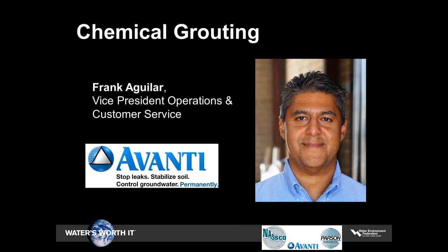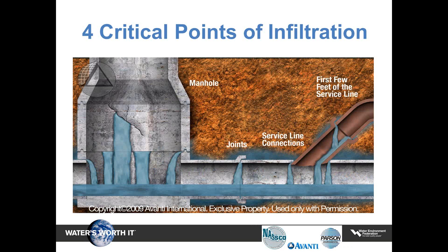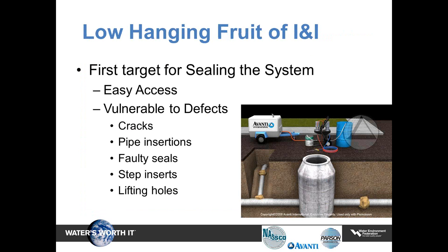Today I'm talking about how manholes are vulnerable to infiltration through cracks, pipe penetrations, faulty seals, and sometimes poor installation. With service line, lateral connection, and main line joints being sealed using a remote grouting packer, the next component for eliminating infiltration is the manhole. Manholes are at times the most accessible with a high rate of return on your efforts — you can see the results right away. The main types of manholes serviced by chemical grouts are brick and mortar and precast manholes. Over time, the mortar slowly erodes away, exposing the manhole to leaks. In precast concrete manholes, the gaskets are rolled or torn during installation, creating an entry area for infiltration.